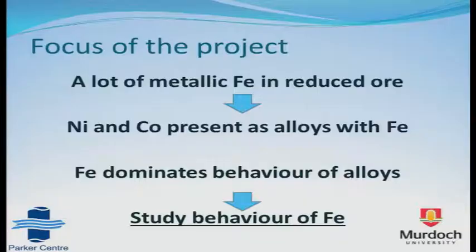Because there's a lot of metallic iron in the reduced ore for the reasons already described, the nickel and the cobalt are present as alloys with the iron, and previous studies have shown that the behavior of these alloys is significantly dominated by the behavior of iron. Many of the iron-nickel and iron-cobalt alloys behave very similarly to just iron. So it makes sense to simplify the problem and study the behavior of iron, because whether it's on its own or together with nickel and cobalt, it is likely to have a strong influence on the dissolution, because you need to dissolve the iron to be able to get to the nickel and cobalt in most cases.